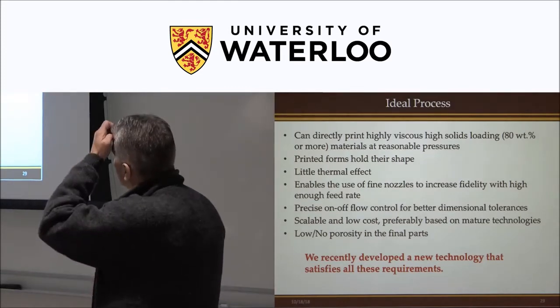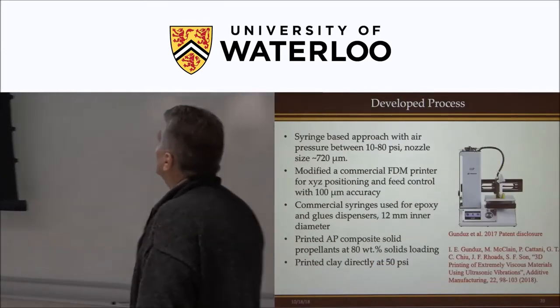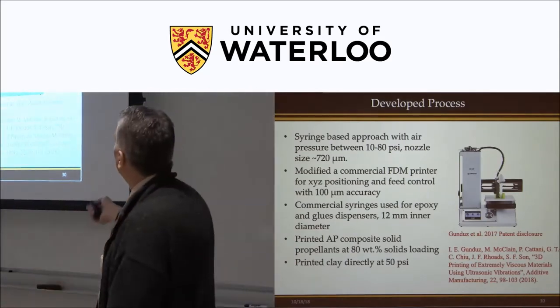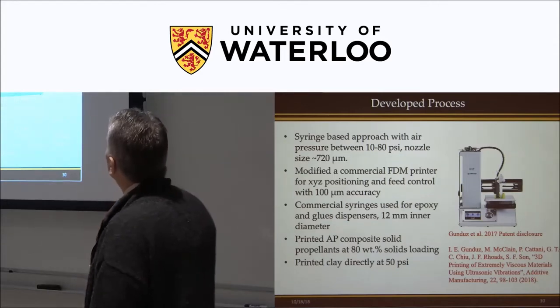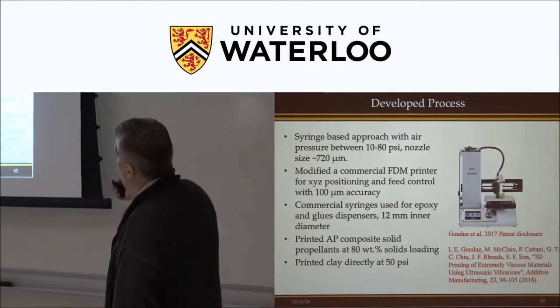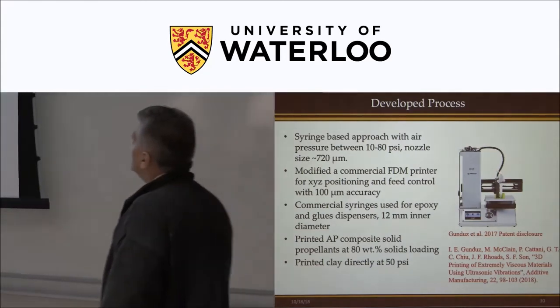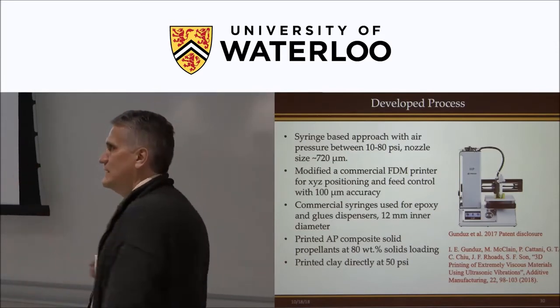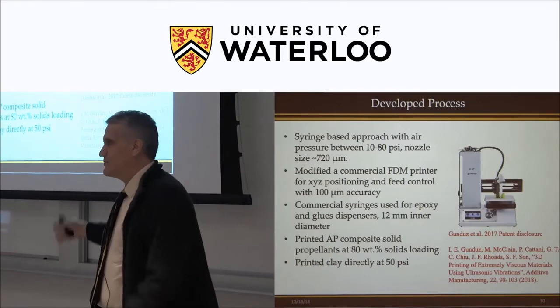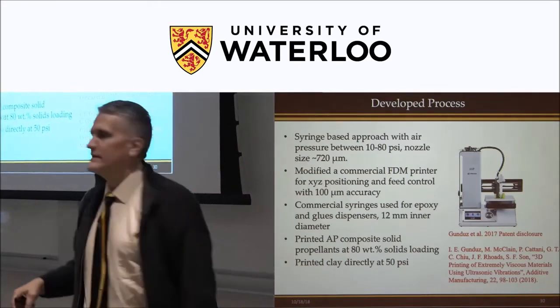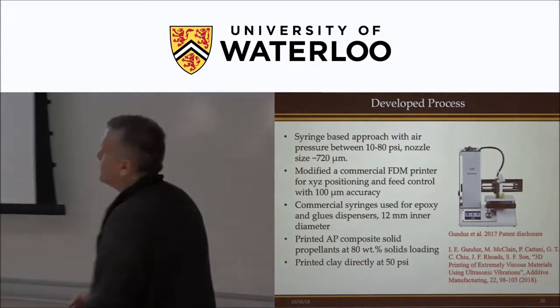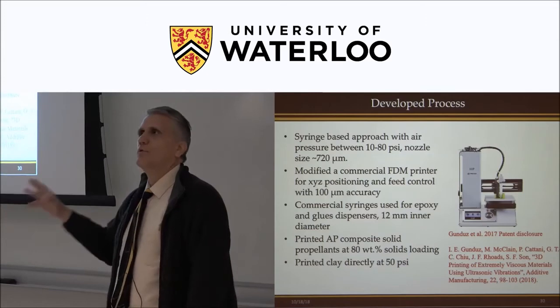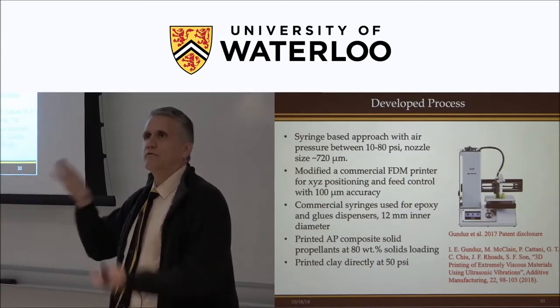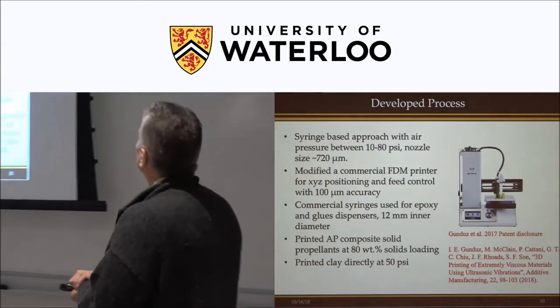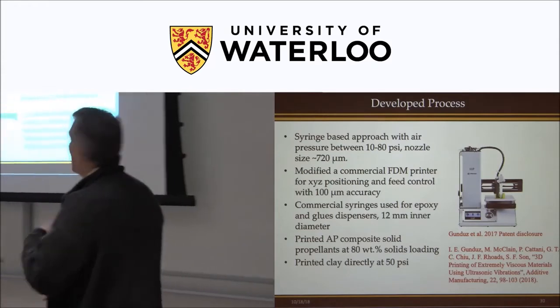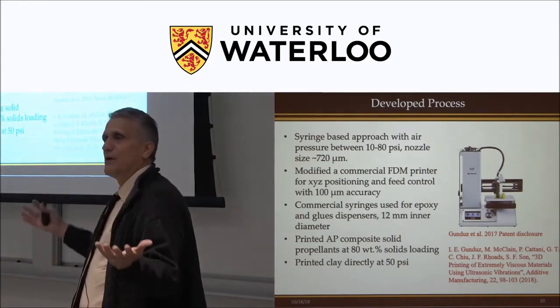So we developed a new technology recently that satisfies all of those pretty well. We started off with just a cheap printer, like a $400 FDM printer. We took all the FDM parts off and added a nozzle. We have a low back pressure, and the secret sauce is a vibration on the nozzle. People say, well, people have looked at putting piezos and vibrating nozzles, this is nothing new. Well, how you do that exactly is new, and in addition, we use the vibration not only to enable the flow, but we actually turn the flow on and off with the vibration. So we have a low pressure that's not enough to move the viscous material, and then when we apply the vibration, that enables the flow. You're all engineers. You probably learned this even in high school.